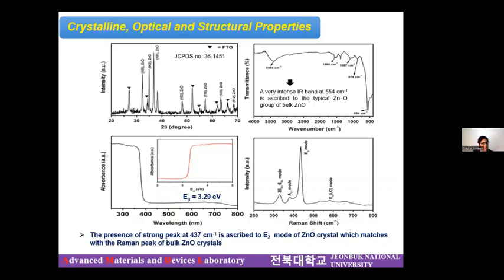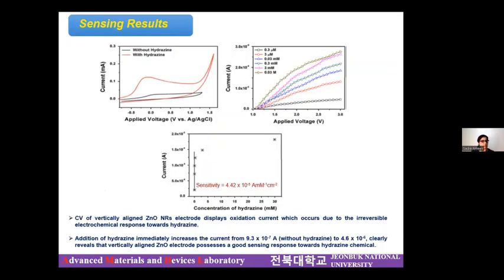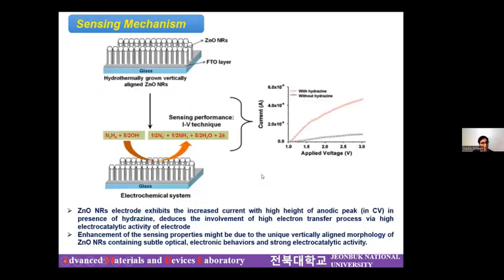These are some of the characterizations that we have performed just to make sure that our ZnO nanorods have been synthesized. And this is the sensing result. Here, through the electrocatalytic activity, you can see the oxidation current: when we have not incorporated the hydrazine, which is the analyte here, the current response was actually nothing. But when we incorporated the hydrazine, the oxidation current increased, and it shows a high sensitivity of this much value. And briefly, we have shown how this happened, that is, the sensing of hydrazine over the surface of the ZnO nanorods.